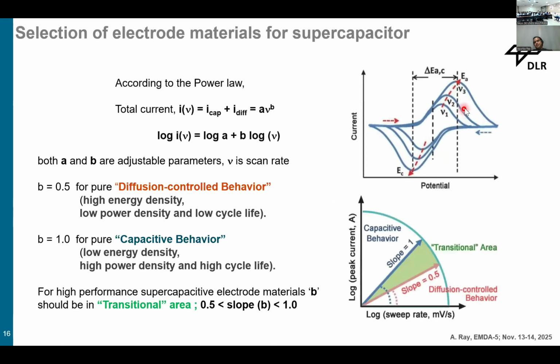For material selection, if you work on the development of materials, once you develop a new material, you first check the cyclic voltammetric curve, and from the peak position you can calculate or explain your material properties. The first is the peak current, which comes from the power law. This peak current is the contribution of the capacitive current and the diffusion current, or redox current. The general equation is i = a times the scan rate to the power b. If you plot log peak current against log sweep rate, you will get the slope value b, and this b value gives you information about your material.